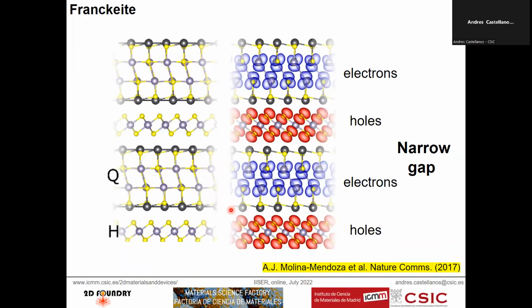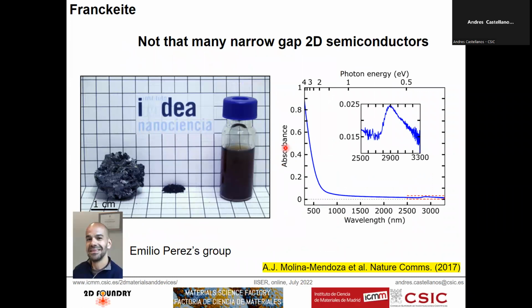Our friend Juanjo Palacios did some DFT calculations, and this material has a narrow gap. And interestingly, the electrons and holes get separated in space. So it's a type 2 sort of superlattice, where holes live in these H layers and electrons live in these Q layers. So that makes it interesting, for example, for time-resolved optical spectroscopy studies. In collaboration with Emilio Perez at IMDEA, we fabricated inks, these suspensions of Franckeite platelets, and we studied absorbance, and we saw that it absorbs under 0.5 electron volts. So it has this exciton peak over here, which is telling us that it's indeed a very narrow bandgap semiconducting material.